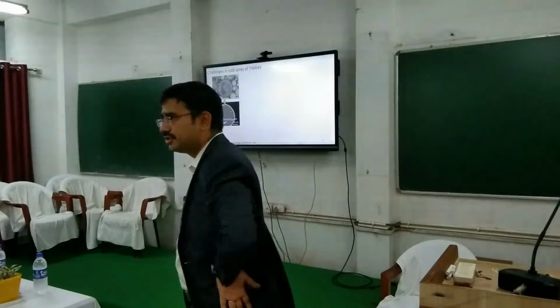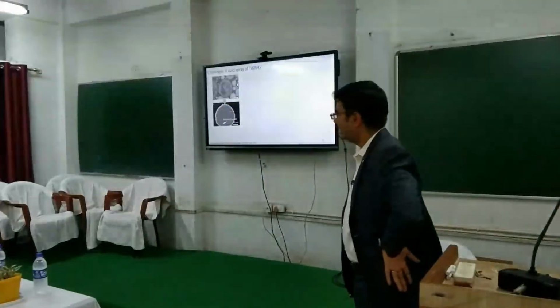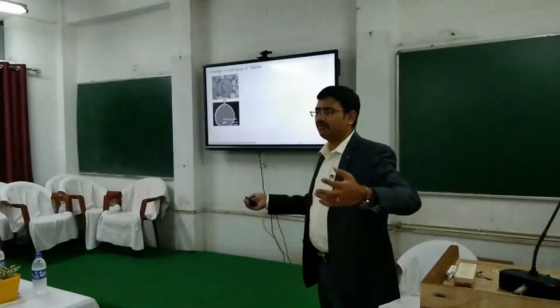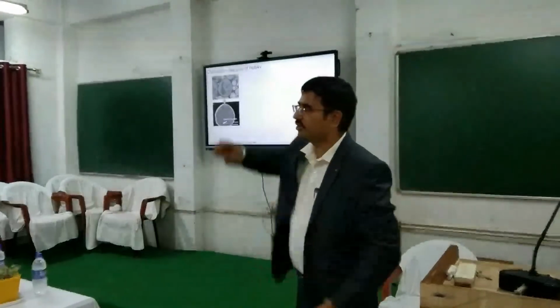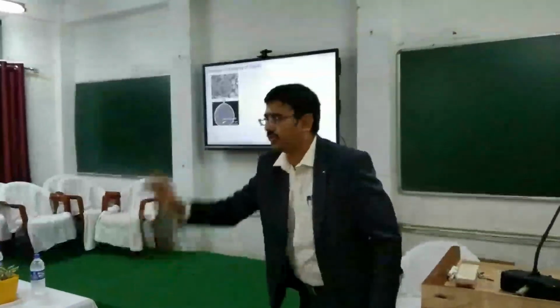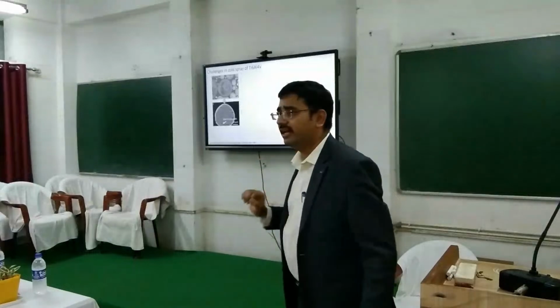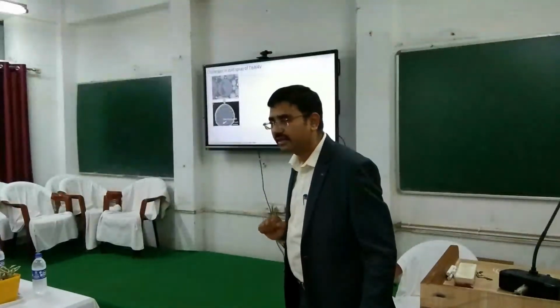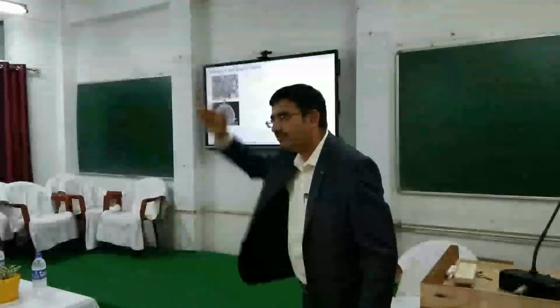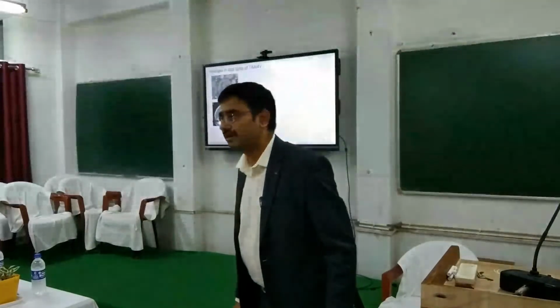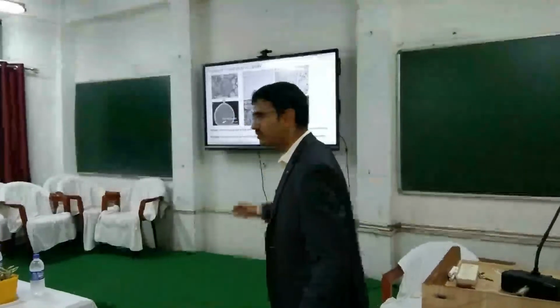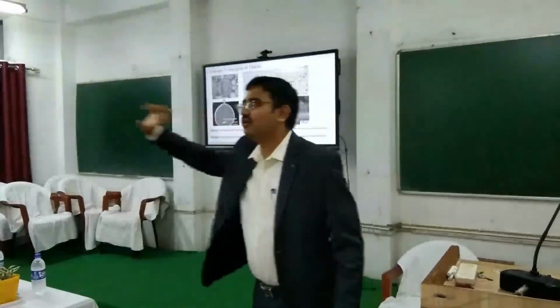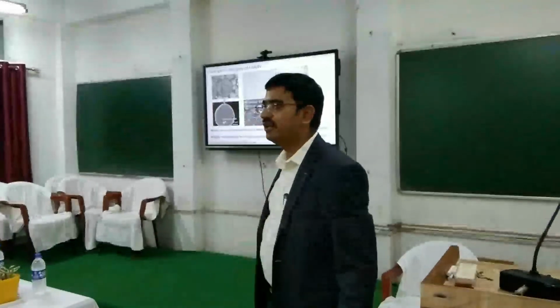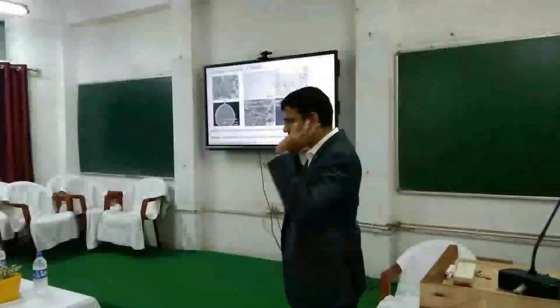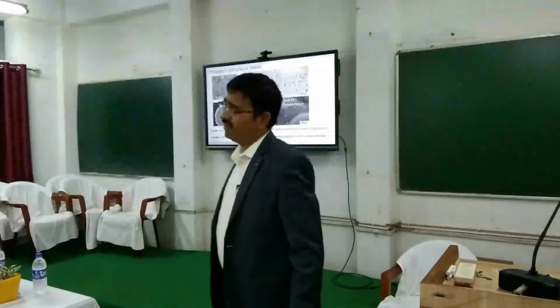But there are some challenges in cold spray. If you look at the powders which you use for titanium and titanium alloys, they are manufactured using a gas atomization process where you have rapid heating and then you cool it immediately to get spheroidized powders. Titanium has a phase transformation at 890 degrees centigrade from BCC to HCP, and since it's a fast cooling, you will have a martensitic microstructure which is very hard, and when you cold spray it, since it is hard, it is difficult to deform. So as a result, when you are using nitrogen as the propellant gas to accelerate the particles, you end up getting very porous coatings.